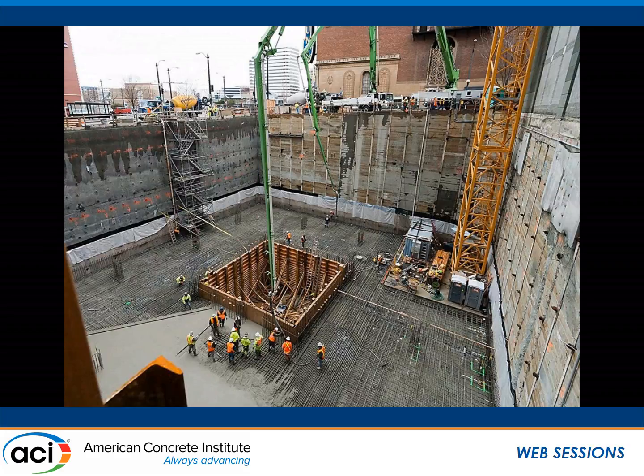We had high-strength steel in the mat, top and bottom rebars. In some areas, you can see here, all number 11 bars, and we had about 4 inches on center on some of these bars. There's multiple layers. But it turned out to be great. They poured it in one pour, about 5,000 cubic yards.